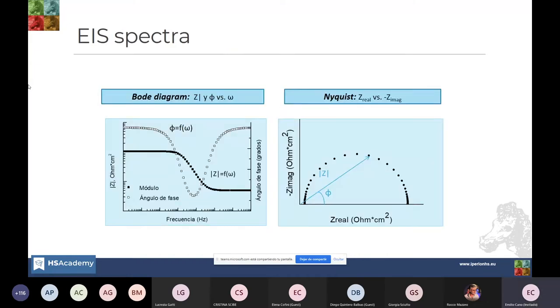The typical EIS spectra can be presented in different ways, but the most typical ones are the so-called Bode diagrams and Nyquist diagrams. In the Bode diagram shown here on the left, we represent the modulus of the impedance and the phase angle of the impedance versus the frequency. And this is the typical aspect you can see.